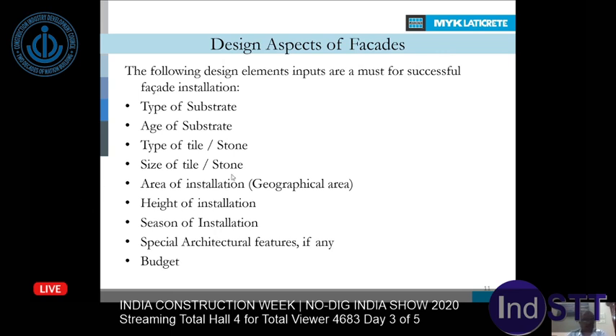And the area of installation, whether it's a highly rainy area or a dry, hot, or humid weather, accordingly you have to select the right adhesive or setting materials. In the same way, height of installation is very critical, because when you are fixing a tile 40-50 feet high, you make sure that gravity is not pulling down the tile or stone, so you have the right fixing material. And also at what season you are installing these tiles or stones, because that again matters. If it's very hot weather, you may not have high workability, so you have to make sure you have the right, long working material when you're working in dry hot weather. Or if it's a rainy season, again you have to make sure that the material is intact and not having problems with setting during the rainy season.